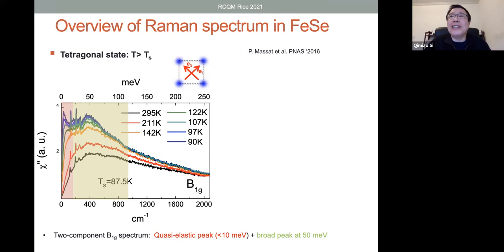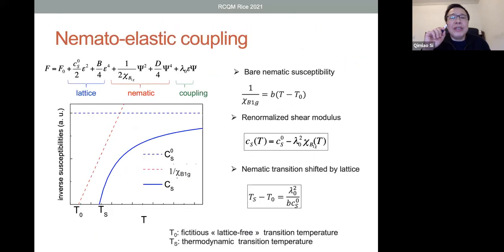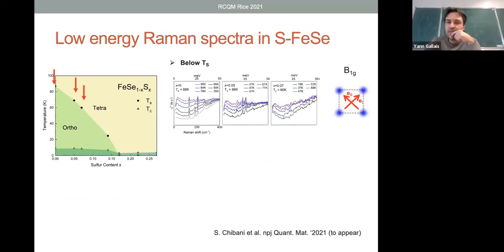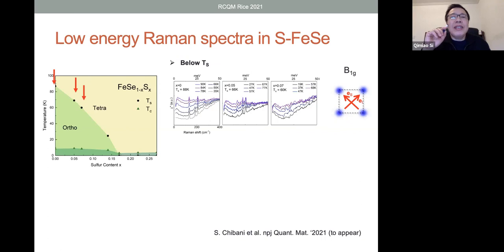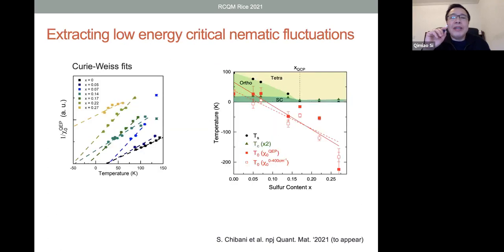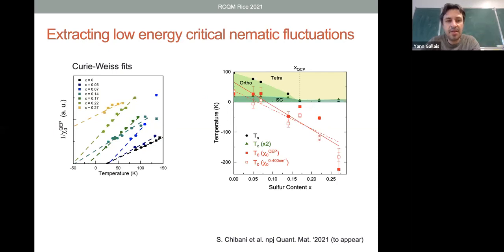But transport to me is harder to interpret. I was more thinking about Raman, which is probing some correlation function which we know what it is, or elastoresistance, something that probes a nematic channel or any other channel where one sees singular behavior in the temperature dependence. So maybe if you go to, let's see, 5% or 10%, you say T0 goes to 0? Yeah, that would be between 5 and 10%. And do you have a temperature dependence of this Raman-derived susceptibility? Yeah, that would correspond to something like the blue here.